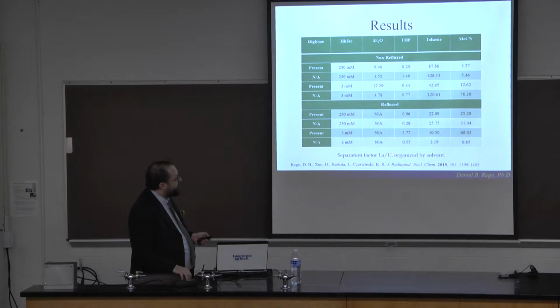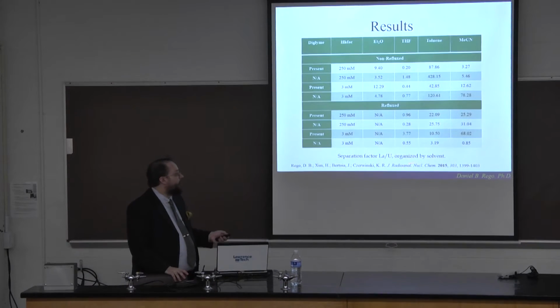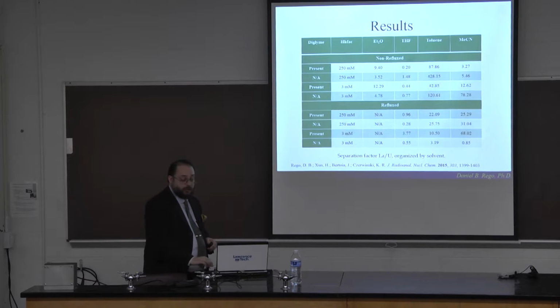I should note that the cerium didn't really react at all, and the praseodymium was intermediate in reactivity between the lanthanum and the cerium. And since most lanthanides form trivalent oxides, this would work well for the vast majority of the lanthanides.